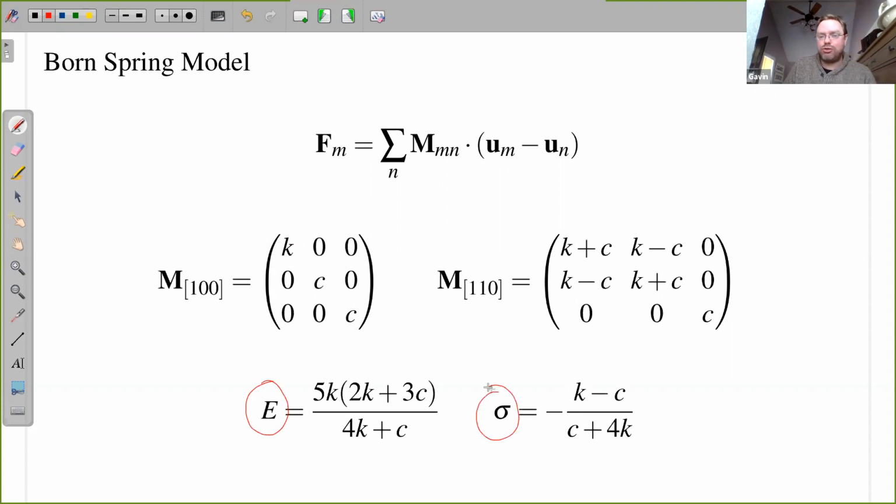the Poisson's ratio. Now, for the Poisson's ratio, if you put C equal to 0 in this, the K's will cancel out, and this is where the limit of a quarter comes in. It's a third in 2 dimensions and a quarter in 3 dimensions. So this is the limit in terms of how good you can get this to be in mapping your Poisson's ratios on.